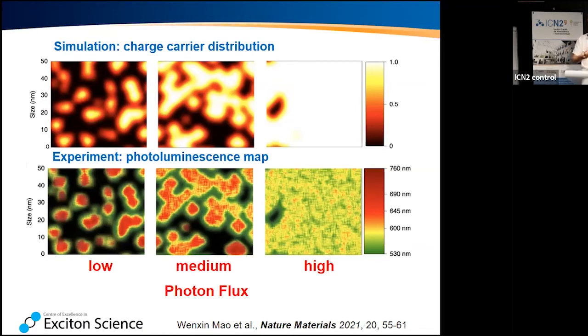And that is a self-reinforcing mechanism: once you form these kinds of halide segregations, this is where it keeps. But then if you start having more and more carriers in your material, the gradients change. Here you have a lot of gradients. If you think about being an iodide ion that can move in the perovskite, moving from here to here gives you a lot of gains. But once you have the high intensity light, then as an exciton, the whole perovskite will more or less look the same. So you don't have that driving force anymore for segregation. So that's a model developed by our colleagues at the University of Sydney.